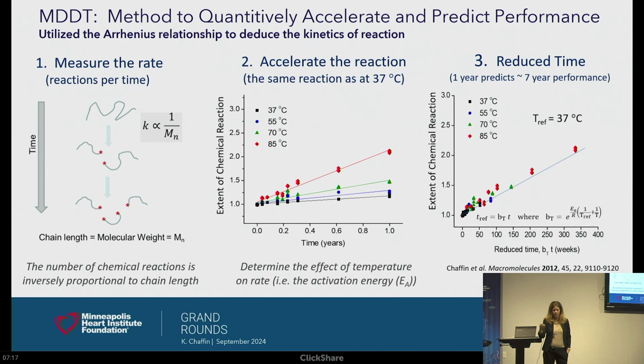So if you're going to predict a rate of a chemical reaction, we have to count number of reactions over time. You guys remember that from your chemistry class? So that's a rate, reactions over time. So if we measure the length of those polymer chains over time, one reaction reduces the molecular weight on average by 50%, 2 reactions on average to a third, and so on and so forth. If we plot 1 over molecular weight over time, that's a rate. So that's what I'm calling this Y ordinate. That's the extent of chemical reaction. I just saved you from the math on there. So we can measure that chemical reaction at many different temperatures. This is what you take advantage of when you put your food in the refrigerator so you don't have your food spoil.